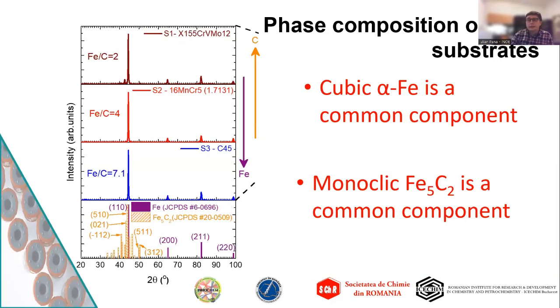The XRD analysis of the steel substrates revealed that iron is a common element shared by all of them. One observation concerns the steel 1 substrate. Besides the cubic alpha iron phase, which is common for all the substrates, we saw, particularly for the S1 substrate, the monoclinic iron carbide phase, shown here in orange. This is due to the heat treatment of the steel substrate.